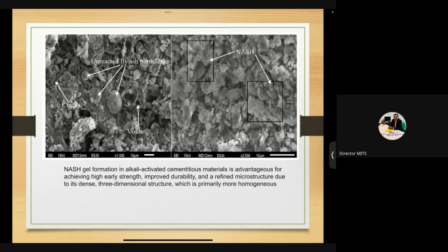And if you see here, the microstructure, this is actually SEM one. If you see the left side and the right side, unreacted fly ash particles, you could see the arrows, you could see the cracks, you could see the voids. Whereas on the other side, after reaction, NASH, you don't find any type of crack, any type of void. I hope you can see, this is the microstructure at SEM level.